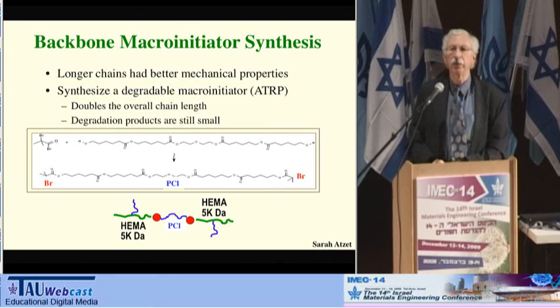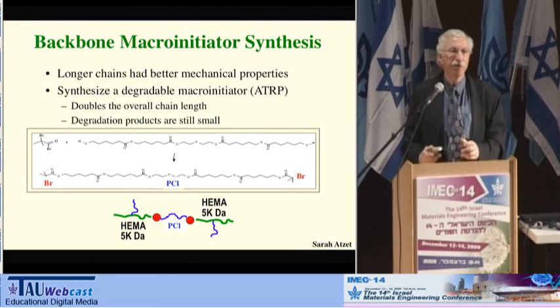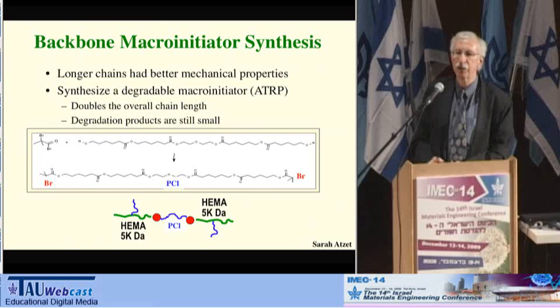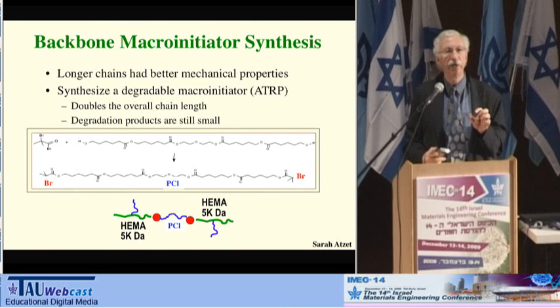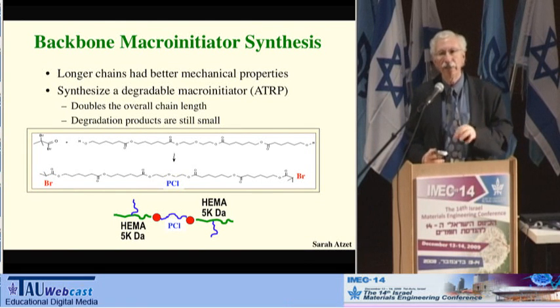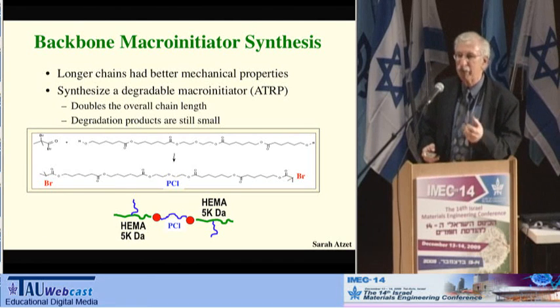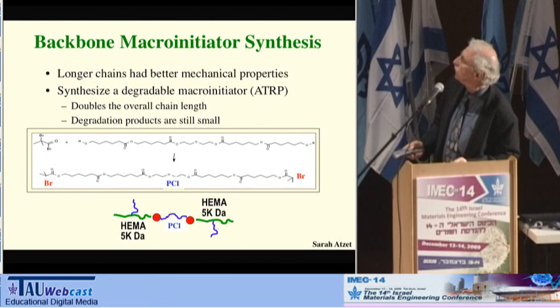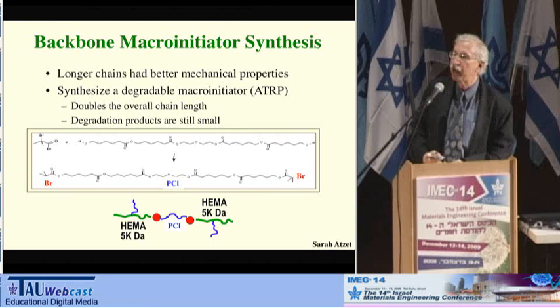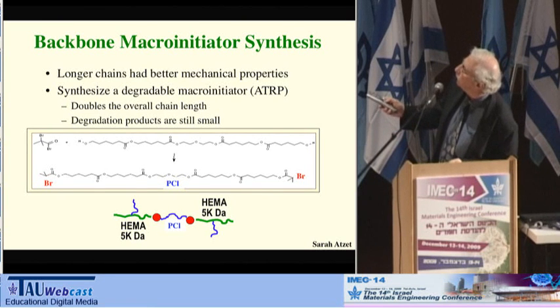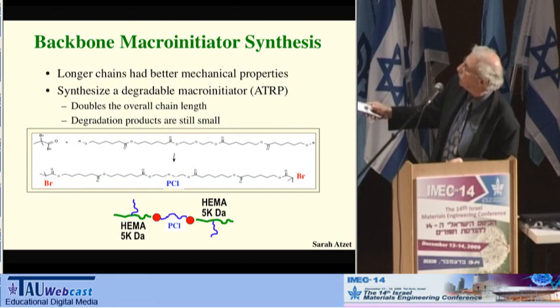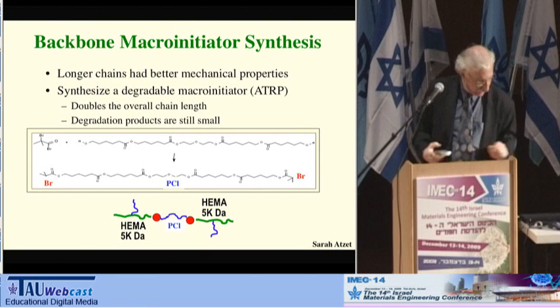The problem with that: we made that polymer, it certainly degraded appropriately, but it had very poor mechanical properties. The 5,000 molecular weight units were simply not quite macromolecular enough to give macromolecular type properties. So one of my PhD students, Sarah Atzet, developed a polycaprolactone that has these ATRP initiators at the end and allows her to initiate HEMA chains off a degradable segment. So now we have in the backbone a polycaprolactone unit and crosslinks.